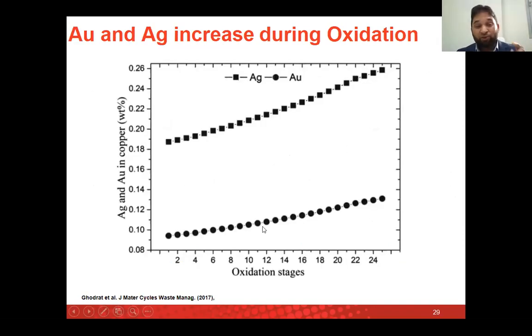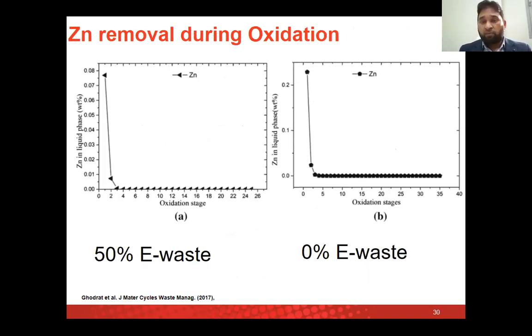But at the same time, you see during the oxidation stage what is happening? The concentration of our gold and silver is increasing. They are not coming from any source; they were present in the black copper, but now we are removing other impurity elements, and the concentration of gold and silver is increasing. There's nothing happening to them basically. This shows that they are not lost during the oxidation step. They are not being lost in terms of gas or some reaction, because they don't make any oxide or become fumes anyway.